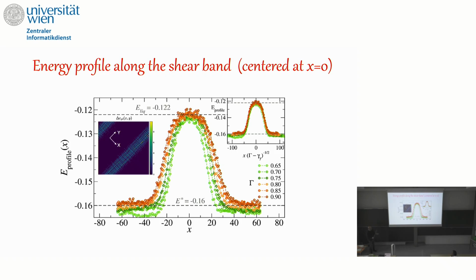So this phase is a mixed phase, and this is a picture of the accumulated strain along one period. You see the strain, for half a period, because otherwise it would be negative. The strain accumulates along this shear band. And if you integrate over y and look at the energy, you see that this dark part here corresponds to the energy minus 0.16, so the energy of the solid, which is the solid at the transition. And the energy in the shear band is exactly the energy of the liquid that I showed you before.